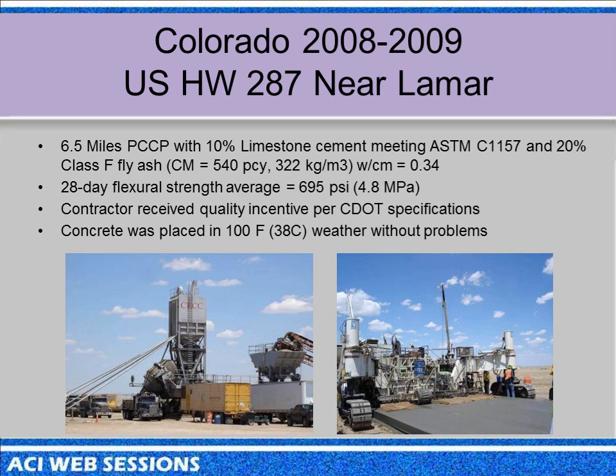Due to time, 6.5 miles of concrete pavement, 10% limestone, 20% Class F ash, pretty low water cement ratio for the paver. And they were getting their flexural strengths, and the contractor got a quality incentive based on, I guess, uniformity and quality. And this was done in hot weather, in some cases up to 100 degrees Fahrenheit. And so they were able to do this, and they didn't encounter any problems with the limestone cement.